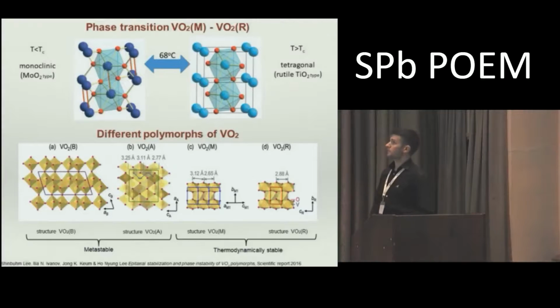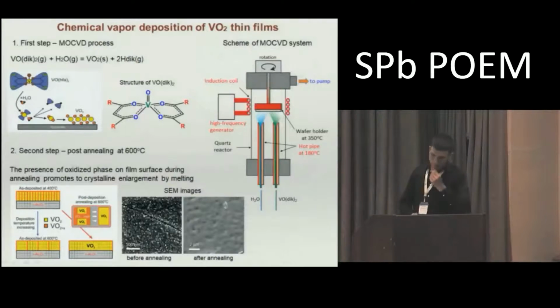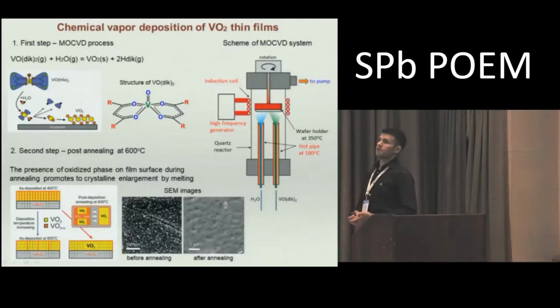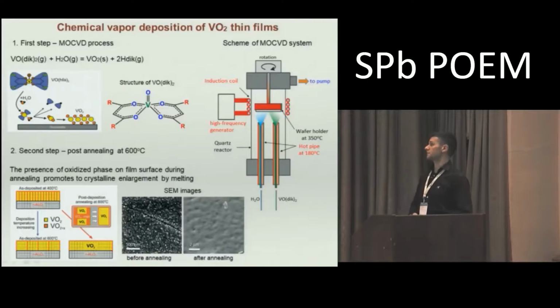Not only these two polymorph modifications of vanadium dioxide can be formed in experiments, but also other metastable phases of vanadium dioxide. Phase B and phase A are metastable, and these phases in the films have a negative influence on the electrophysical properties. So we have a solution for obtaining high quality epitaxial thin films.